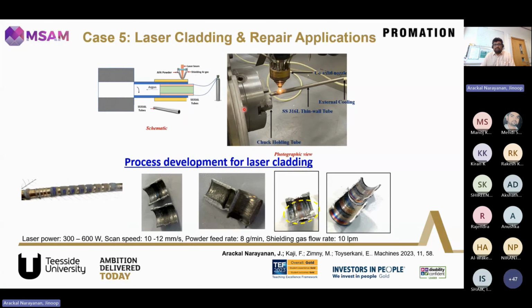Another challenging and important work that we did was on a cladding application for the nuclear sector. We did a cladding on a 0.5 millimeter thin tube. This is for a corrosion resistant application for a small modular reactor, so it's more towards the nuclear energy side. We had to develop a coating which is highly corrosion resistant and oxidation resistant. Because of the limitation of thickness of this tube, it is really challenging to develop such a coating.